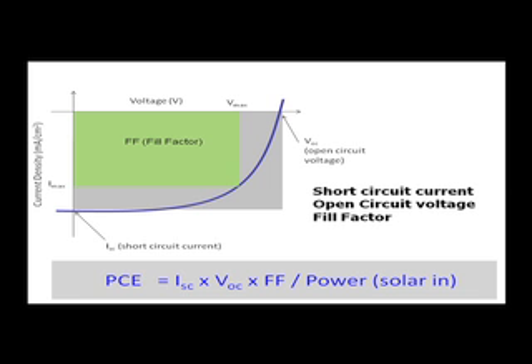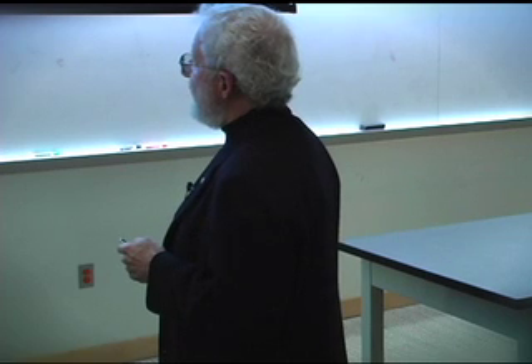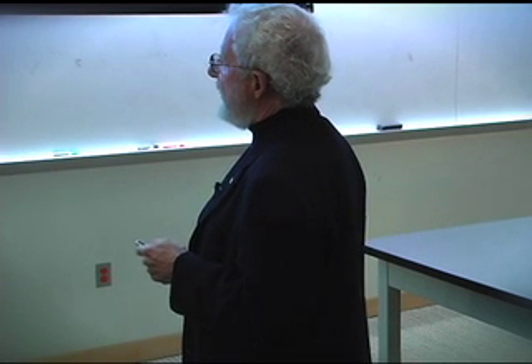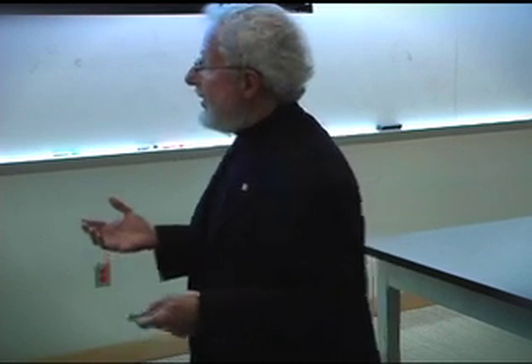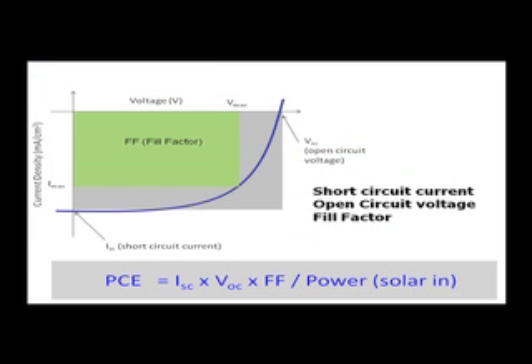So that means that the efficiency that I can hope to achieve is a product of the short circuit current times the open circuit voltage times this fill factor, the ratio of these two areas, divided by the input power. So I need to address these three parameters. I need to make this big. I just told you how to do that. I need to make this big. This depends largely on morphology. And I need to make this big, and this depends on recombination and morphology, and I'll come back to it.